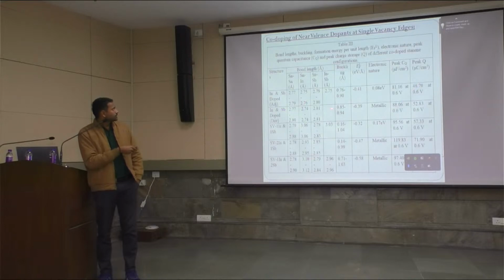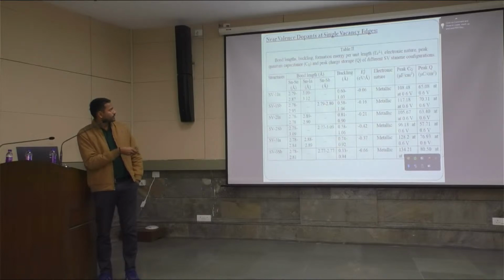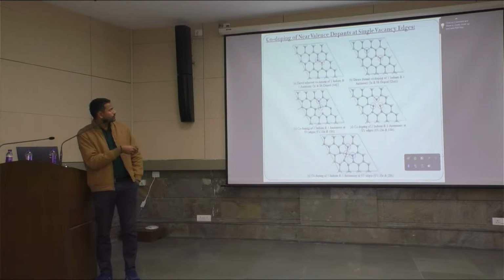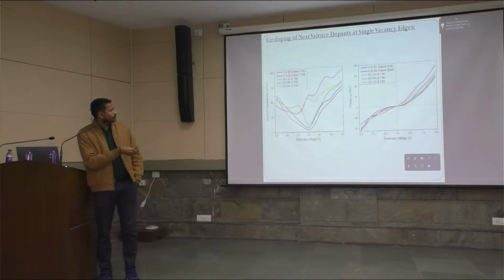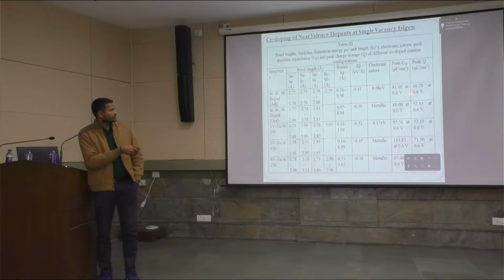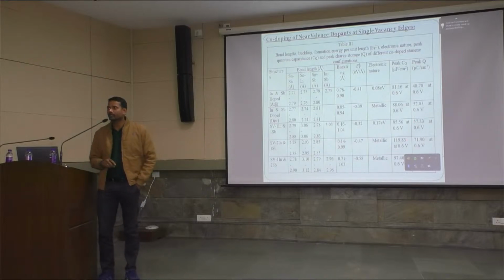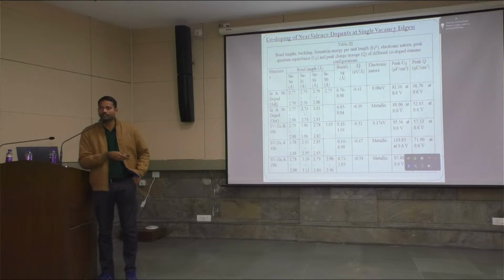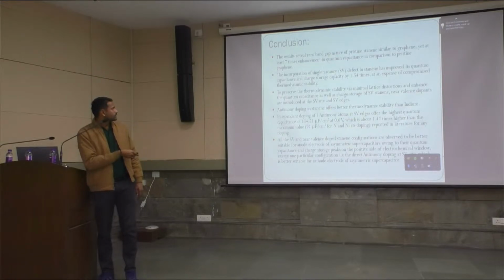And looking at the stability data and the quantum capacitance data, the quantum capacitance peaks are lower in comparison to the individual dopants. And when we dope the individual dopants at the SV edges, we are having better quantum capacitance. But when we are co-doping the indium and antimony, the quantum capacitance peaks are less. So we can say instead of co-doping, it's better to go with the antimony doping in stanene. Yes, this is the conclusion.